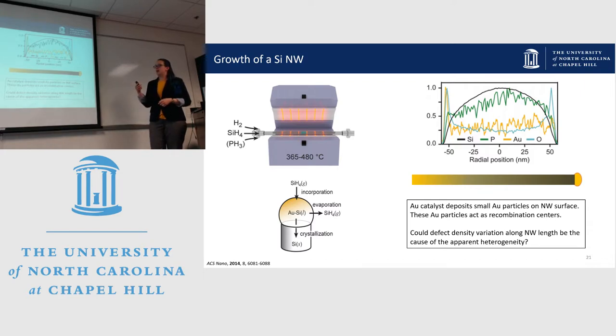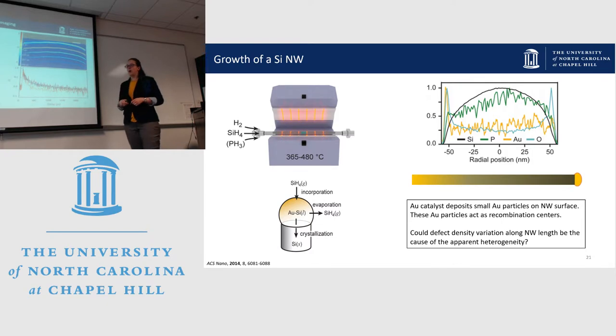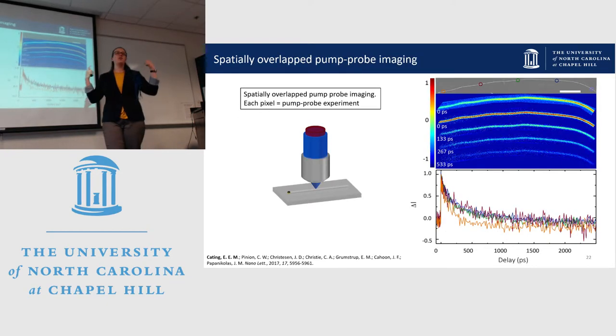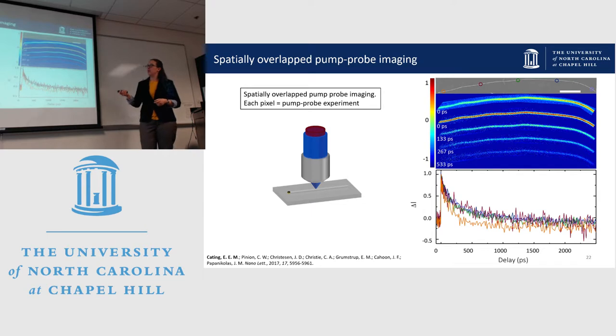So to look into this, I'm going to introduce you to one more mode of operation of our microscope, which is called spatially overlapped pump probe. In this configuration, the pump and the probe are focused to the exact same spot, and we can raster scan the sample underneath, right? And go pixel by pixel and create an image of our wire. So I've done that here for a silicon nanowire at several different pump probe delays. And it looks like the signal decay is pretty much consistent across the entire length of the wire. It might be a little bit faster at this end, but for the most part, it's pretty constant.